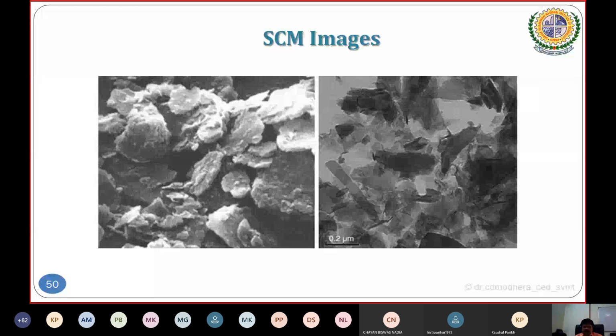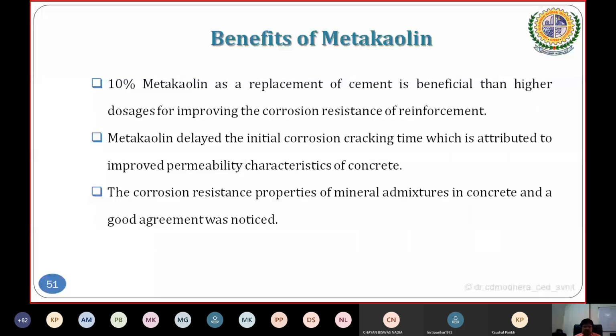This is some of the comments. Because you can always go for more than 10%, but there is a study that if you use more than that, you are not getting its benefit. So the statement shown here is that 10% metakaolin as a replacement of cement is beneficial over higher dosage for improving the corrosion resistance of reinforcement.